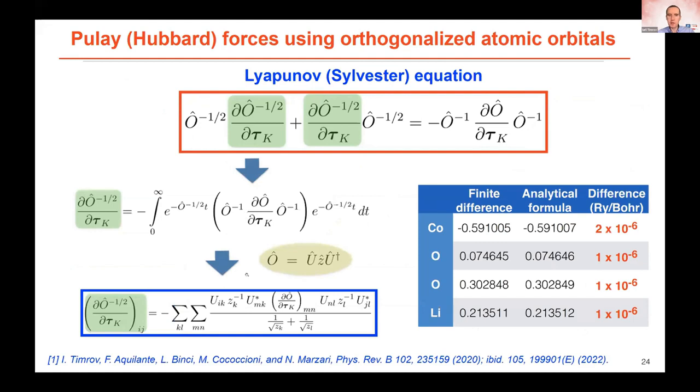It's implemented in Quantum ESPRESSO. And we've just tested that it really gives the exact solution. We compared the analytical formula with the finite differences approach in lithium cobalt oxide, and we saw that the forces computed with finite differences and using this analytical expression match to a high level of precision, which confirms the correctness of the derivation and the implementation. The same exercise was done for stresses.